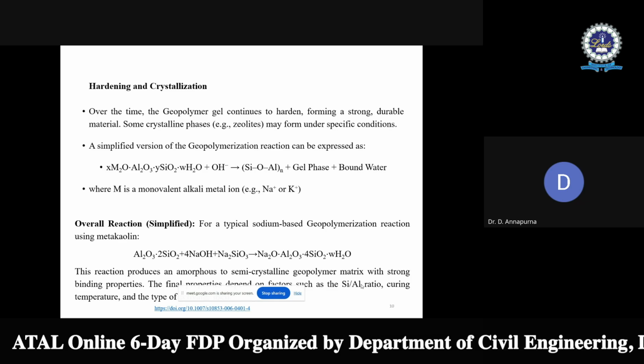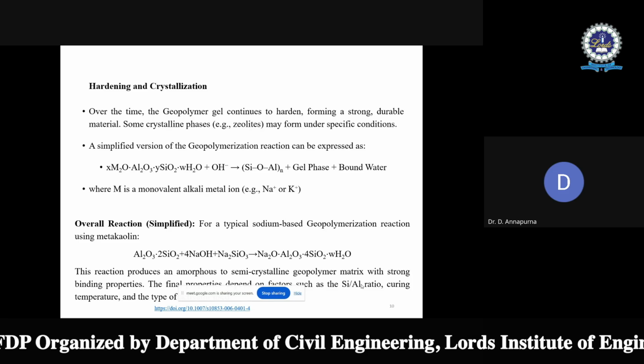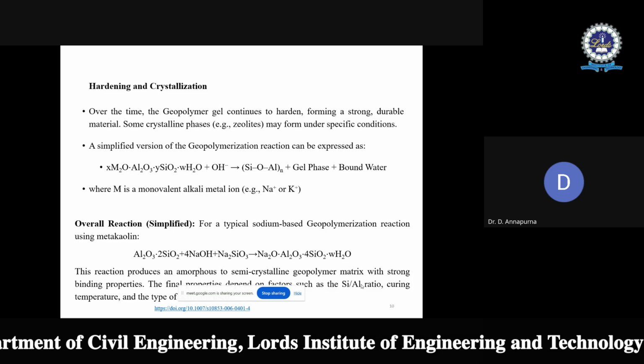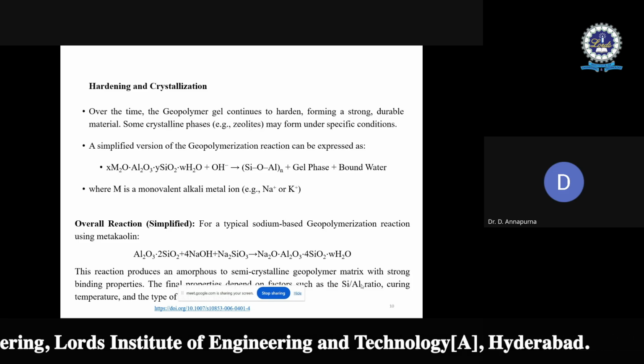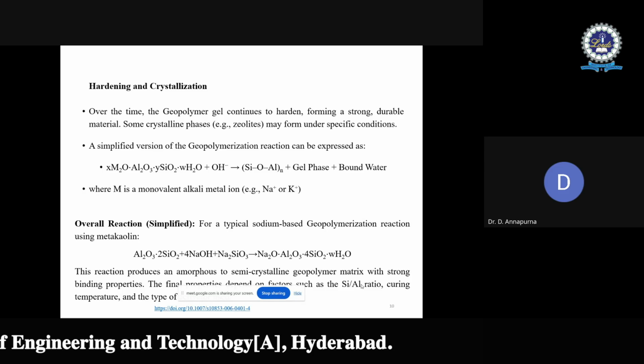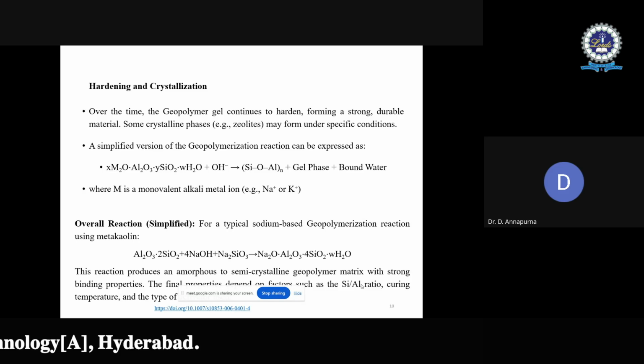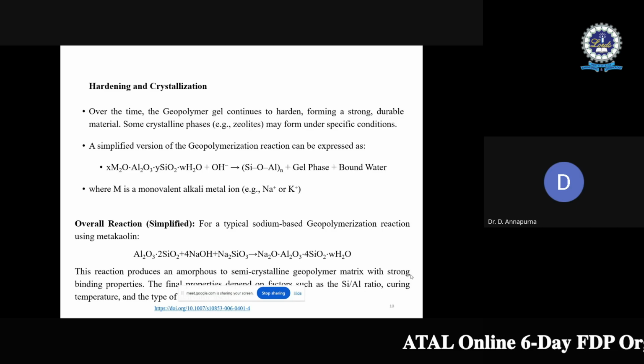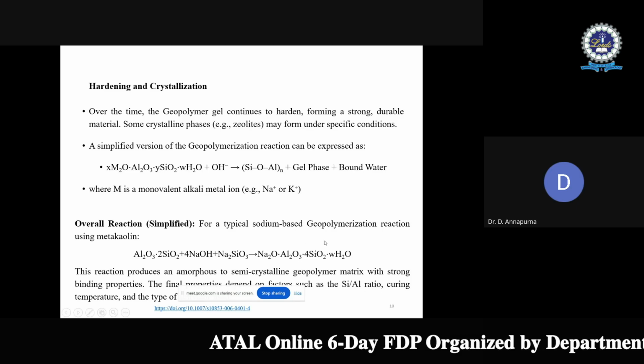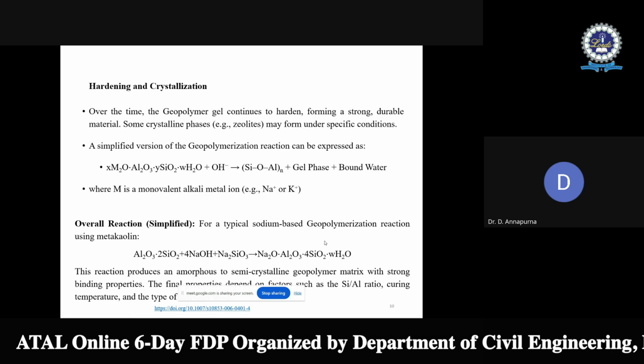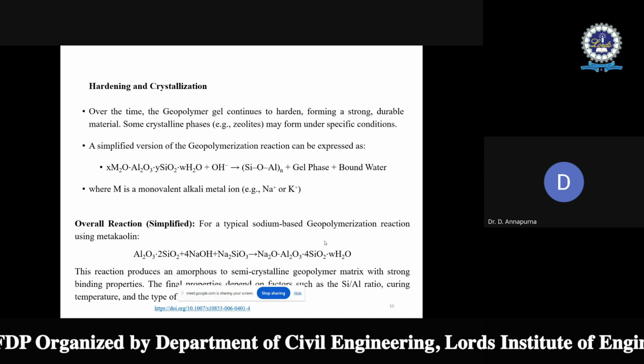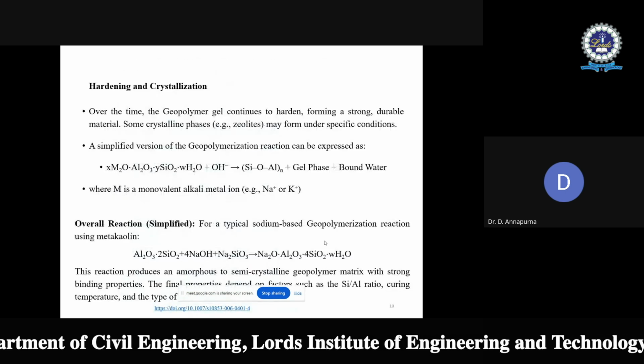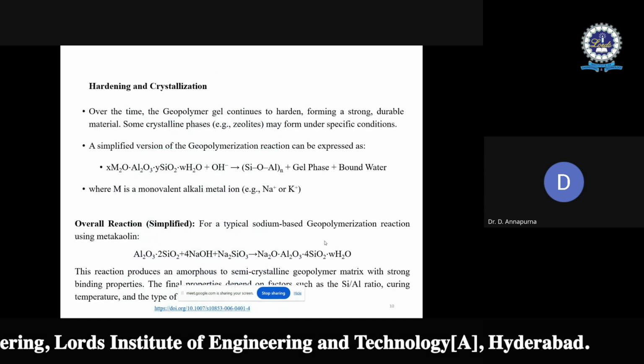Again, this formation depends on the curing temperature, because if we make use of fly ash as the binding material, the fly ash reaction rate will be very slow. To improve the reaction rate, the curing temperature will be increased. And depending on the method of preparation, etc., the final properties will vary slightly. So like this, the geopolymerization process will occur.